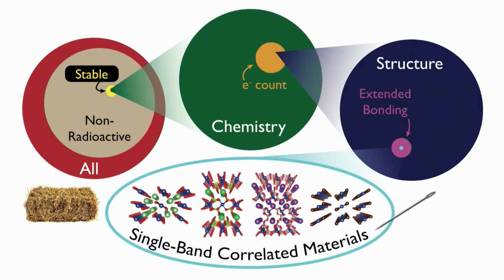So to show you just the kind of scale of this search, I made this figure with all these different circles, which basically we start out with our haystack, basically all known material shown here in red. And as we progressively screen down, our circles get smaller and smaller. So you can see when we go to non-radioactive, then in terms of stability and chemistry, then it gets too small, so we zoom in. We keep screening by electron count and structure. You can almost not see a circle there. We zoom in further, and we get down, when we further screen based on extended bonding. And finally, we've found our 4 or 5 needles in the haystack, these compounds.